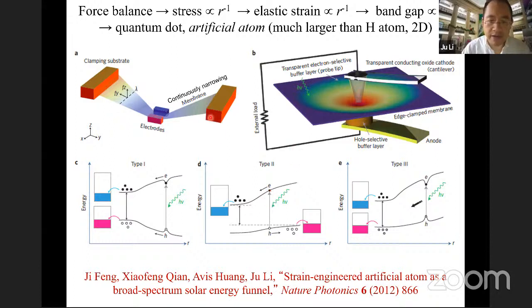But you could also have the electron on the CBM going to the origin, and then the hole bubbles up to the edges. Or because of strong Coulombic attraction between them, you have this charge neutral exciton, and then the electron drags the hole towards the origin. So that's what we call type 3.